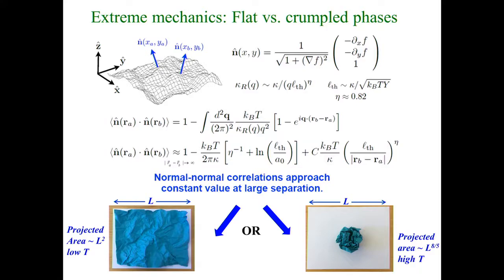And they'll say, okay, what temperature should I use? And then you estimate what that is from this criterion. And sadly, it's 20,000 degrees Kelvin. Okay. Not going to happen. The water's going to boil well before you get there. You do it in a vacuum, the chemical bonds will fall apart before you get up to this temperature. And then they'll laugh at you and so forth. Well, they didn't actually do that. We realized they would laugh at us.